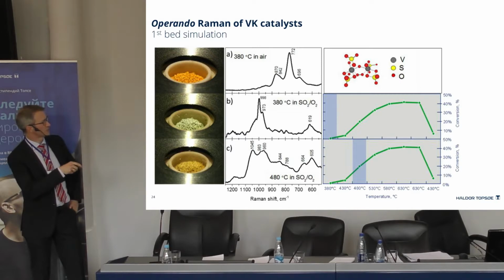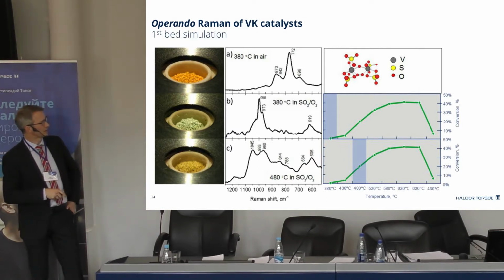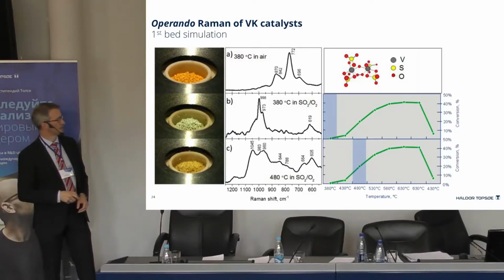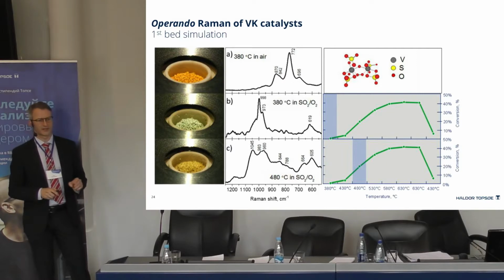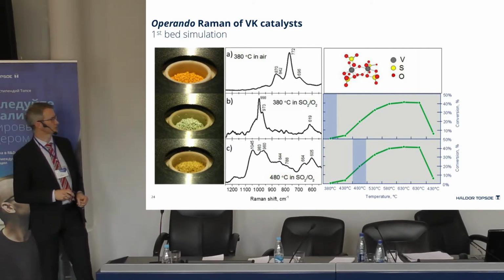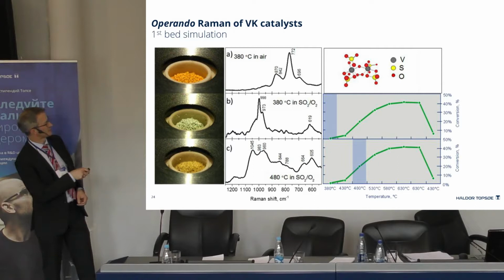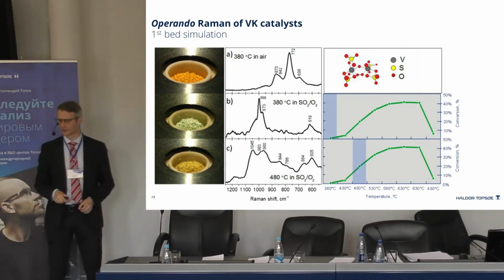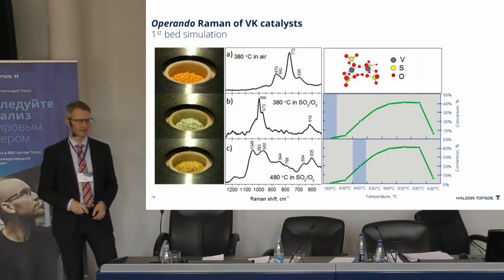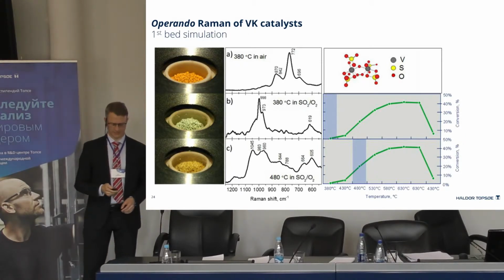When we shift to SO2 gas and we have very low conversion, as shown on this conversion measurement, we get the more green color and the reduced vanadium. When we heat it to 480 degrees, which corresponds to maybe the middle of a first bed in industry, we see again a yellow color, and now we can find monomeric and dimeric vanadium oxosulfate. As you say, it's yellow, but it's a different yellow, so colors are tricky to say anything about the composition.